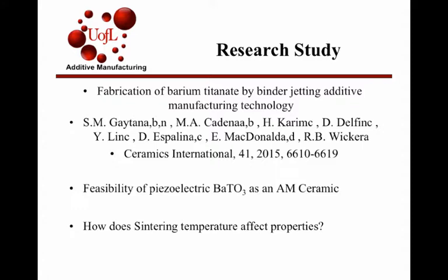The study was done by some guys at UTEP in Texas, called the fabrication of barium titanate by binder jetting additive manufacturing technology. Basically, the study is on the feasibility of barium titanate as a piezoelectric material, and not just how well it works in that application, but also how well it can be additive manufactured through this binder jetting process. One of the main process conditions that they varied was the sintering temperature. So how does the sintering temperature affect these piezoelectric properties of the material?